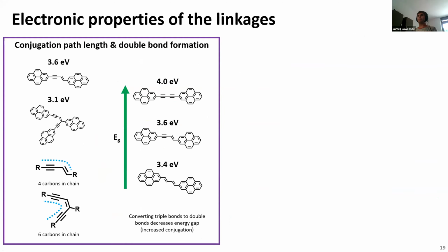So for example, we can consider things like the length of the conjugation path. As you increase the number of, for example, single-double bond chains between these pyrenes, we can decrease the energy gap. This is particularly apparent when going from triple bonds to double bonds between these pyrenes, because it seems that these triple bonds don't conjugate very well between the pyrenes, possibly because of the symmetry between them. But when we increase the number of double bonds, we get quite a 0.6 eV lowering of this energy gap.